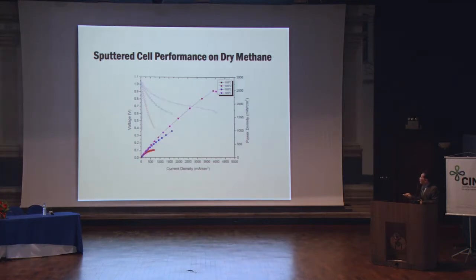But one thing I'd like to show you here is the sputter cell performance on dry methane. Actually, this caught us by surprise too, because at 700 degrees C, we got 2.5 watt per square centimeter with dry methane. I believe that this is the best performance ever reported for operation of SOFC with dry methane.